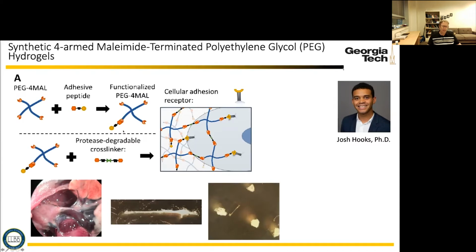The advantage of this is it's highly tunable, so we can control the degree of cross-linking, and so how stiff the gel is. We can control its degradability. We can control presentation of growth factors, peptides for matrix attachment, and sites for cell adhesion. And so Josh Hooks, who was a former Ph.D. student in the lab, took this platform and